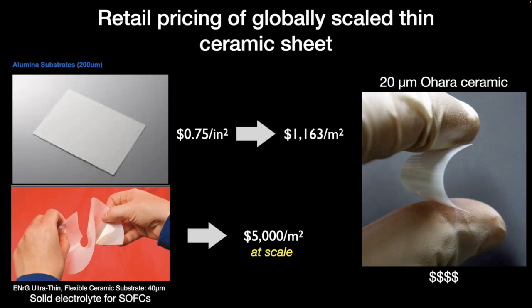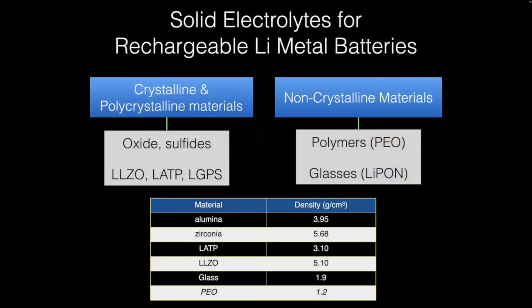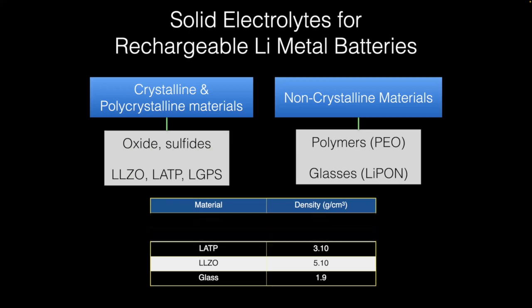We're 10 times that thick. So this is a problem. And then if we go back and look at the world of crystalline and non-crystalline materials for batteries, oxides, sulfides, polymers, you have to, again, look at density and actual cost of scaling. So here are three interesting materials: LATP, garnet LLZO, which is quite dense, and glasses, which are actually closer to the density of polymers, and that's a plus.